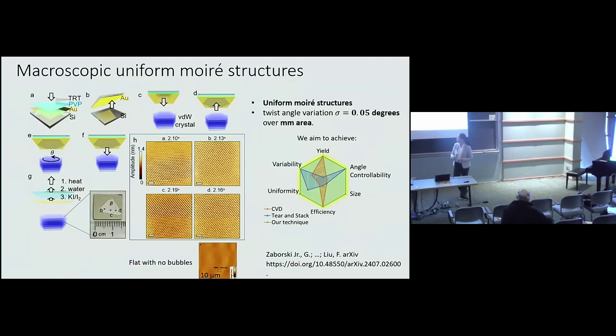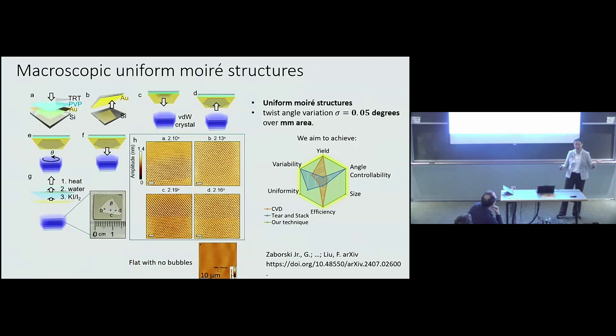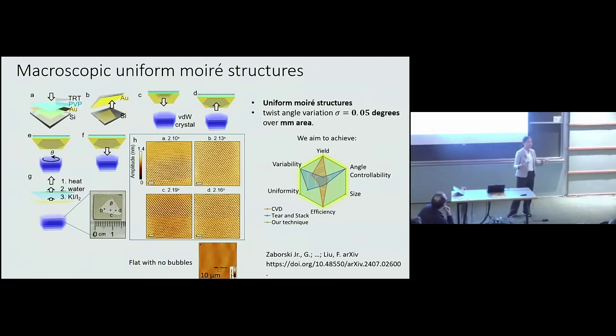So we have tested thermal stabilities for 2 different angles. The stuff I have just showed you is 6 degree. And we have also done another test at 2 degree twist. At 2 degree twist, if you heat it under similar conditions, the twist angle would relax very little, to less than 0.1 degree, after we heat it for hours. So if you can imagine this for the twist bilayer on the micrometer scale, they would relax back and lock right away. Okay, thanks.